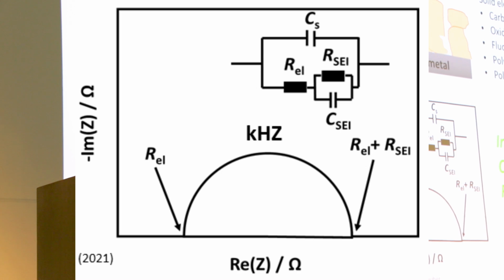On the other hand, we can do some spectroscopies that we know from the spectroscopies of thin films. The most typical one that is used in the battery community is XPS. However, if you ask thin film people about XPS, they will just start pulling their hair out, because it has actually been developed for very flat, thin films with very ordered structure, not containing all of these messy phases, not being very rough as we know it.